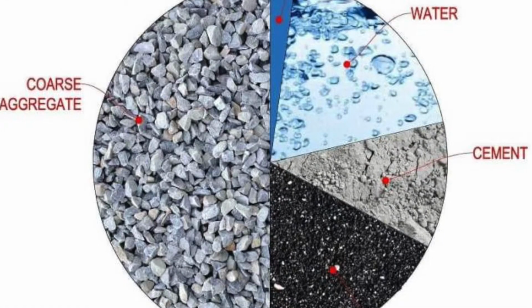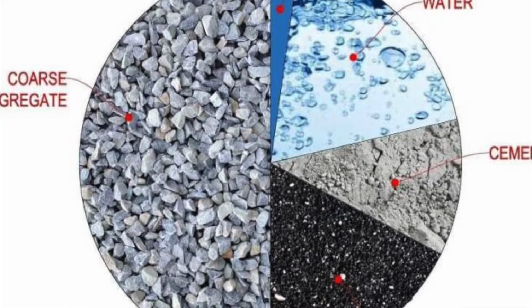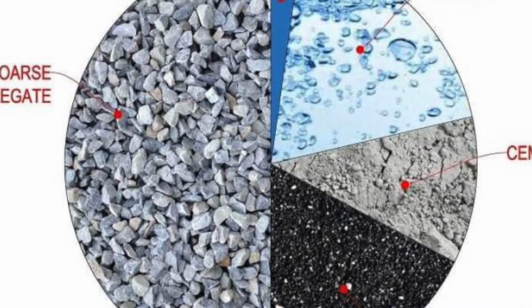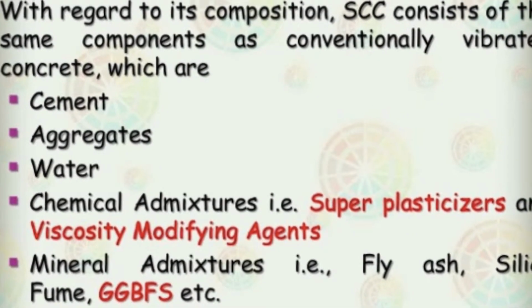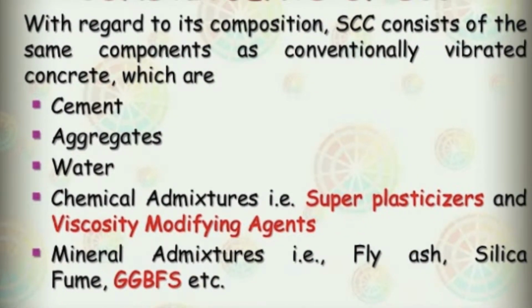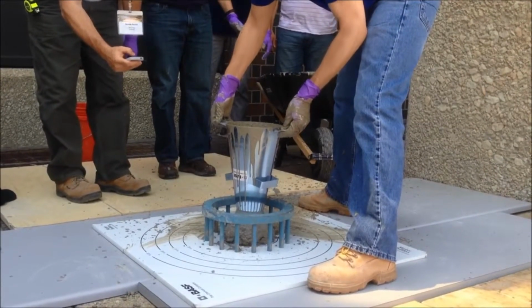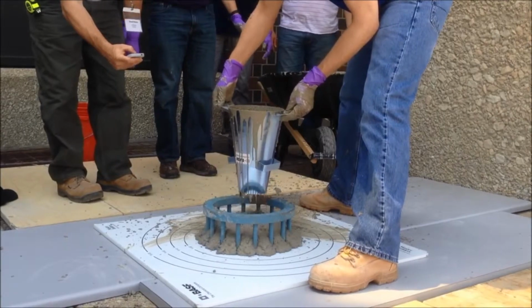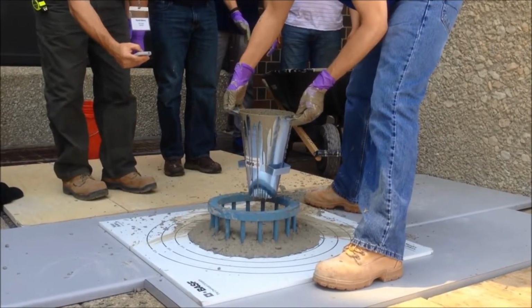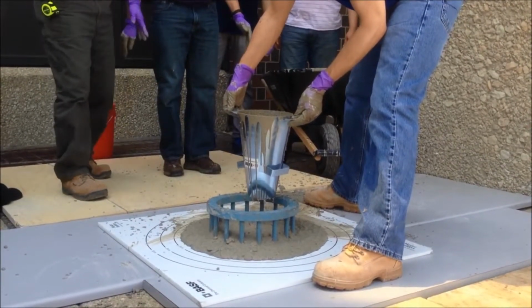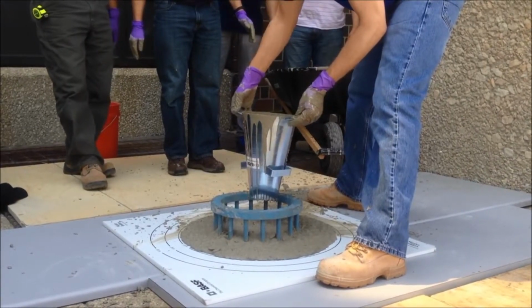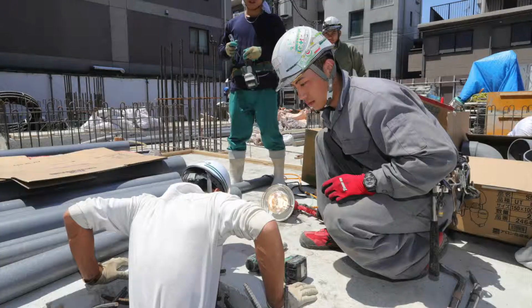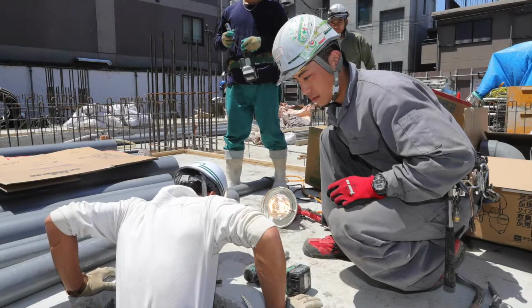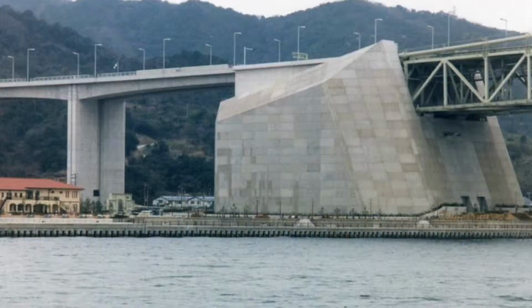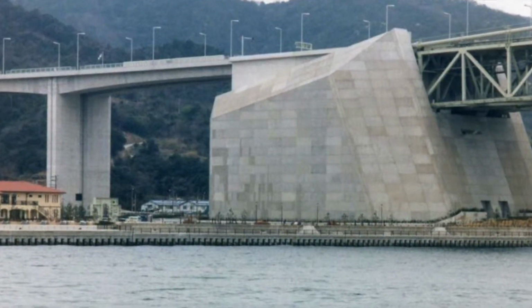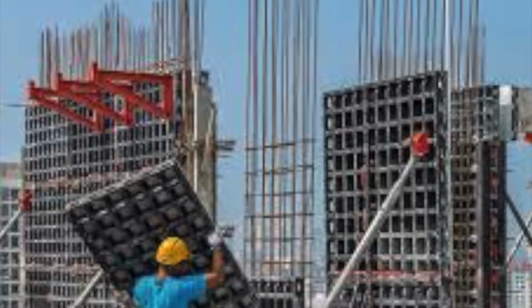The first prototype of self-compacting concrete was achieved using materials that were readily available on the market. It served very well with regards to self-compactability and other properties of concrete, both in the fresh and hardened states. In fact, it was considered a high-performance concrete by all standards, and by the early 90s, Japan had developed and adopted the use of self-compacting concrete in general.